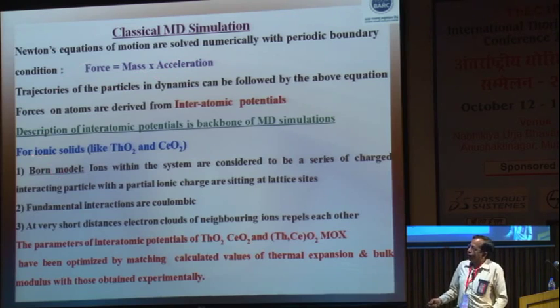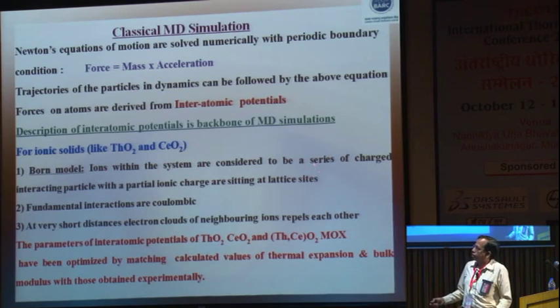And then for an ionic solid, we invoke the Born model, in which ions within the system are considered to be a series of charged interacting particles with a partial ionic charge sitting at lattice sites. Fundamental interactions are Coulombic, and at a very short distance the electron clouds of neighboring ions repel each other. So, with these three assumptions, the parameters of interatomic potentials of thorium oxide, cerium oxide and mixed oxides have been optimized by matching calculated values of thermal expansion and bulk modulus with those obtained experimentally. I will just highlight these in the next few graphs.